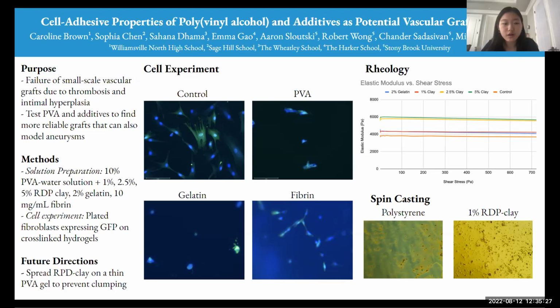We also conducted rheology tests to analyze the stiffness of the gels, and we discovered that the elastic modulus increased with the clay concentrations and that the gelatin gel had an elastic modulus similar to that of the 1% RDP clay. We also tested the thrombogenicity of our solutions by spin casting them onto silicon wafers with the polystyrene solution as a positive control. We added fibrinogen solution to half the wafers to compare results. And we found that fibers only grew on the samples with polystyrene as expected and not on any of the ones with clay, indicating that the PVA RDP clay solution is not thrombogenic, which is a positive result.